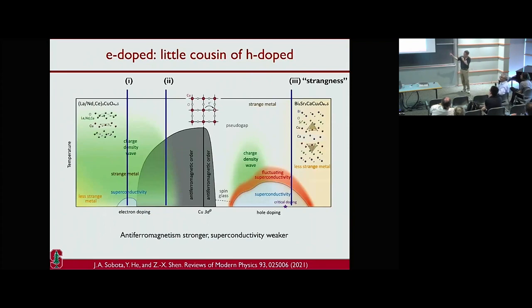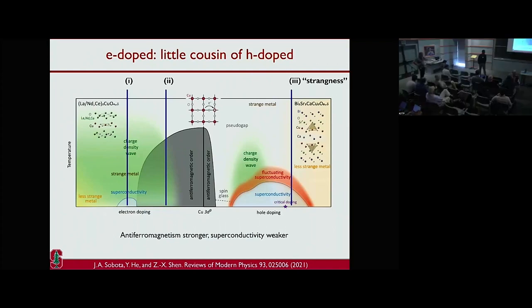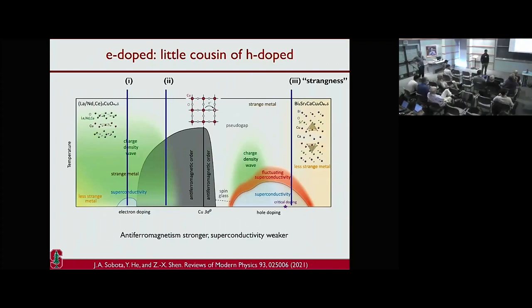This situation is that we are not in the regime with the long-range order. 15% is beyond the long-range. But Martin has shown within the plane you still see a pretty strong correlation. So I can't give you the answer at zero temperature experimentally. One more question, and then we can stop. Well, we started late, I think, also.